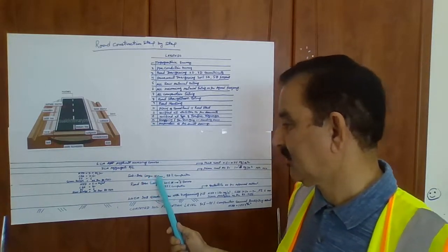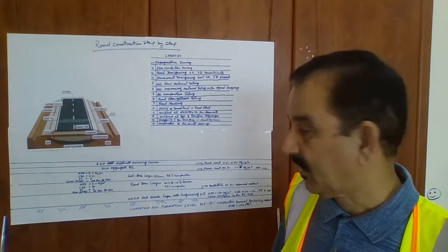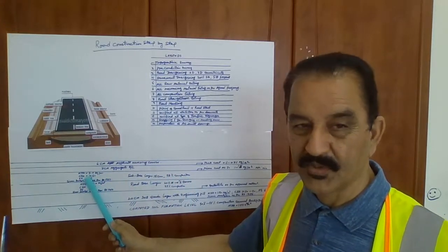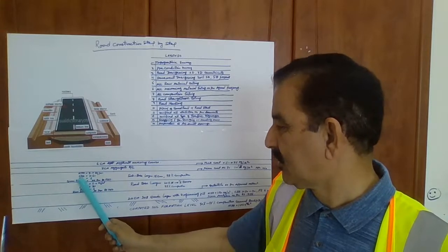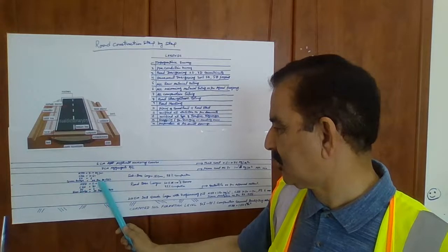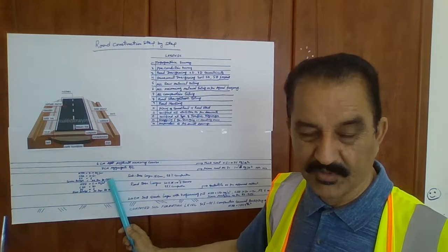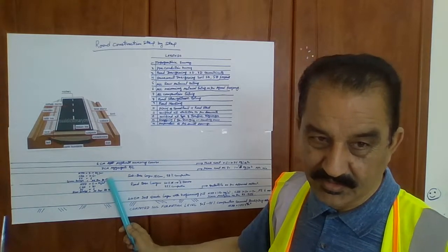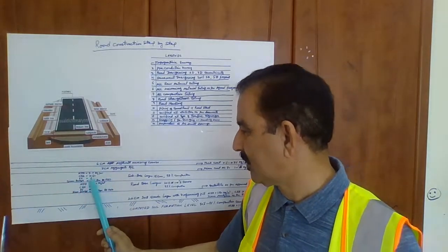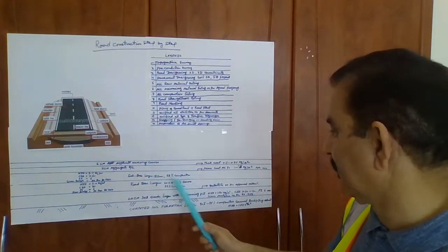Then the sub base, 15 centimeters or whatever the spec says. This one is 98% compaction. MDD is 2.0 grams per cubic centimeter. CBR is greater than 60. Atterberg limits analysis as per BS 1377 or ASTM, whichever standard is recommended, and also the PI is maximum 6. So these are the steps we are going through.